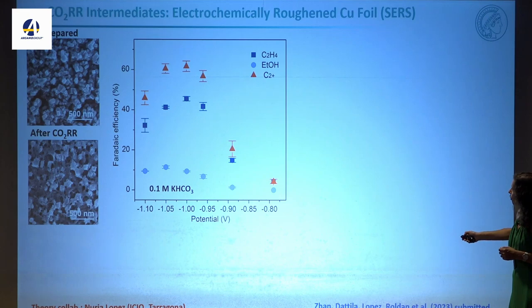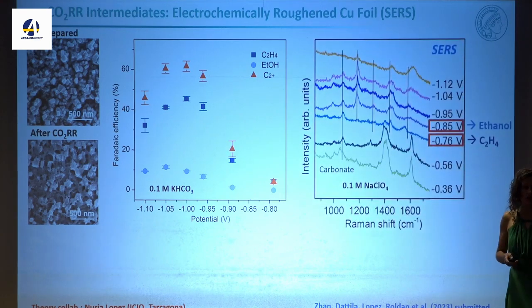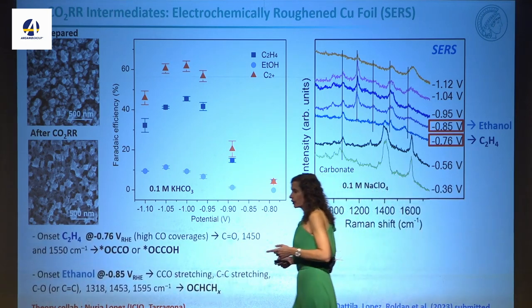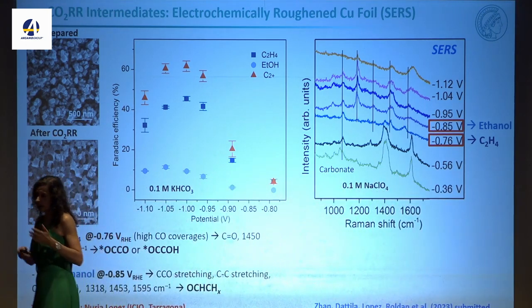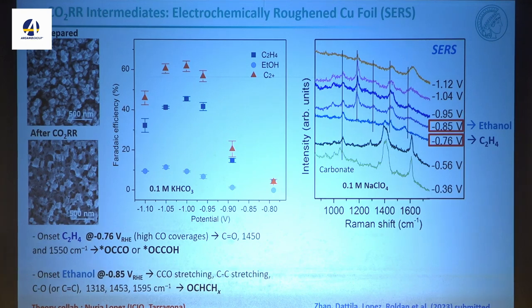So this is the production of C2+ products. Here is ethanol that starts a little bit later than the production of ethylene. And if you look at the Raman data, at the different applied potentials, here is when we start making ethylene, here is when we start making ethanol. There are clear differences, again, you can see this by eye, in the spectra. So we could see that we can detect, first of all, not only CO, but now we see other vibrational features. And working again with Nuria López and her postdoc or student Federico Dattila, we could see that at the onset of ethylene, there are these intermediates, and at the onset of ethanol, there are these other intermediates.